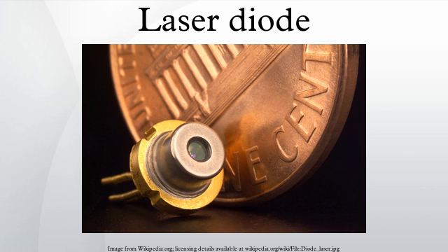In addition, the mirror may heat simply because the edge of the diode laser, which is electrically pumped, is in less than perfect contact with the mount that provides a path for heat removal. The heating of the mirror causes the band gap of the semiconductor to shrink in the warmer areas. The band gap shrinkage brings more electronic band-to-band transitions into alignment with the photon energy, causing yet more absorption. This is thermal runaway, a form of positive feedback, and the result can be melting of the facet, known as catastrophic optical damage, or COD.